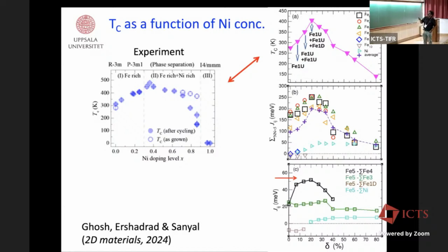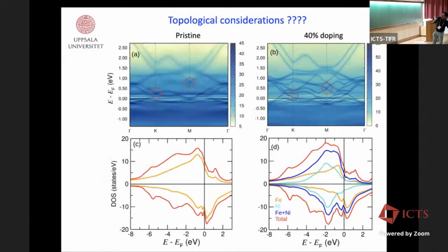Nevertheless, we see this kind of behavior, and we looked into the exchange interaction parameters, and we see that there are specific exchange interaction parameters, specific pairs, the iron 5, iron 4 pair, that show this kind of behavior. And we can conclude that maybe it is happening because of that. The behavior of TC is controlled by this, because it also has the highest value of the exchange interaction.